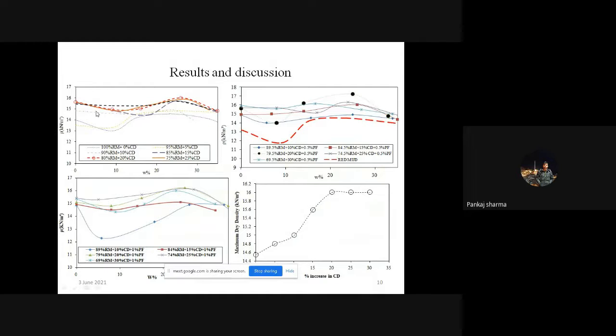Then from the first graph, it is clear that the composition 80% red mud and 20% cement kiln dust shows the highest maximum density among all the different mixes. Then when we add the fiber to this percentage, we see that 79.5% red mud and 20% cement kiln dust with 0.5% of fiber shows maximum density. Further, when we increase the percentage of fiber up to 1%, it is clear from figure number 3 that our density starts decreasing from 17 to 16. Then from the fourth curve, it is clear that the maximum dry density of the mix starts increasing with the addition of cement kiln dust up to 20%.